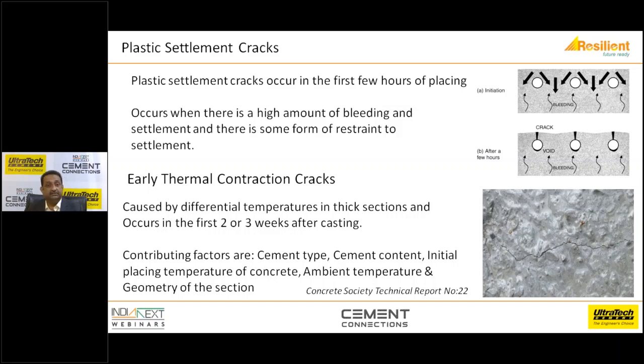The cement content. Now this may contradict with your minimum cement content. So this is a prudence you need to exercise. If you need a minimum cement content, then try to make the concrete within that particular cementitious content. Don't specify very high cement content, because from one end you are creating another problem.